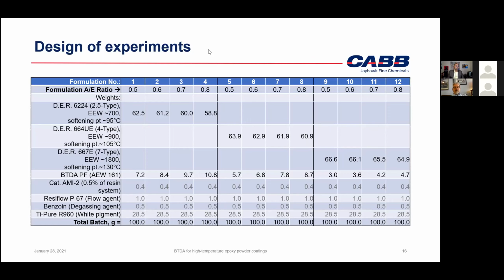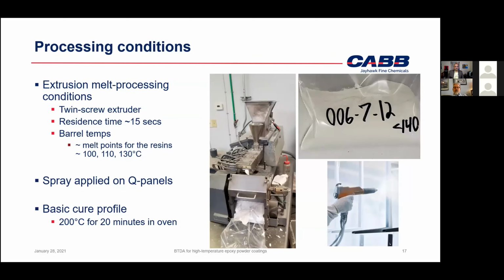We like to keep things simple so that you can see the effect of the part of the formulation that you're evaluating. So we've got a very common flow agent, a polyacrylate, a very common degassing agent, and then just a standard grade chloride process rutile titanium dioxide that's been treated for dispersion and for UV resistance, although UV is not important here. But anyway, the formulations are very straightforward.